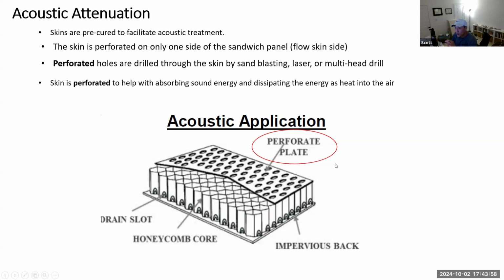So this is an example of a honeycomb core. A flow side skin, which as you can see here is perforated, but this back layer skin on the other side of the core is impervious. There are no holes. You don't want holes on that side. The perforated holes are typically drilled through the skin by multiple different methods: sandblasting, laser, multi-head drill. The skin is perforated to help with absorbing sound energy and dissipating the energy as heat into the air. Basically, the reason it's perforated is because the honeycomb core acts as an acoustic chamber. So the sound waves and sound energy, as the airflow is flowing through that side of the skin, will actually flow into the core itself and basically dissipate the sound energy.